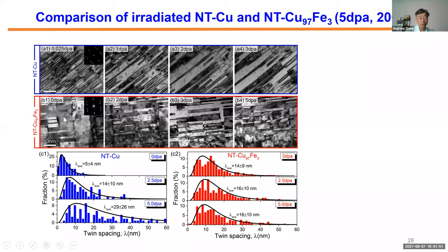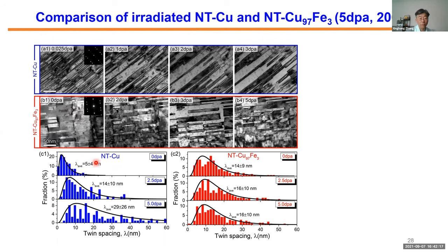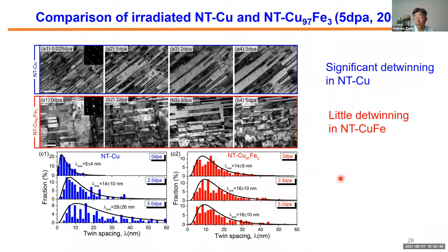But if you do the comparison for nanotwinned copper iron before and after 5 dpa, so this is a little bit higher dose than copper, twin thickness evolution is quite different. For pure copper, what you see here, this is basically twin thickness increase from 5 nanometer to about 29 or 30 nanometer. Sorry, forgot about the laser pointer. So this is 5 to 30 nanometer. And for copper iron, twin thickness used to be 15, and you ended up with somewhere around the same. So twin thickness didn't change much. So meaning detwinning didn't really happen for the copper iron. Right, so this is what we said. Significant detwinning in nanotwinned copper, but very little detwinning in nanotwinned copper iron.